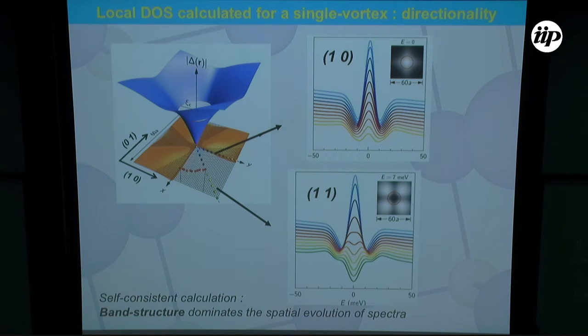So this is a single vortex, a self-consistent calculation of one vortex with the same macroscopic lattice as a background. And you see here two traces going from the center to the outside following the 1, 0 direction. And you see that the zero bias peak does not decay completely. So you still have a zero bias anomaly at a certain distance, while along the other direction, the decay is much more pronounced. And this is a fact which is quite important, and it's essentially due to the band structure of the material.